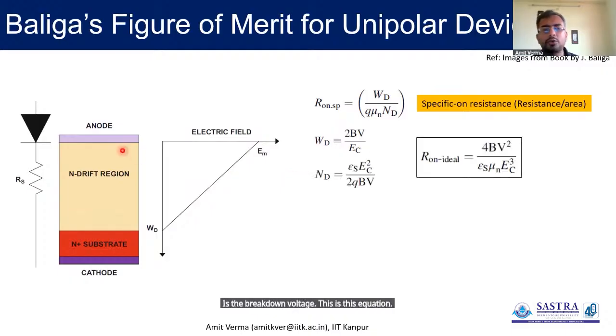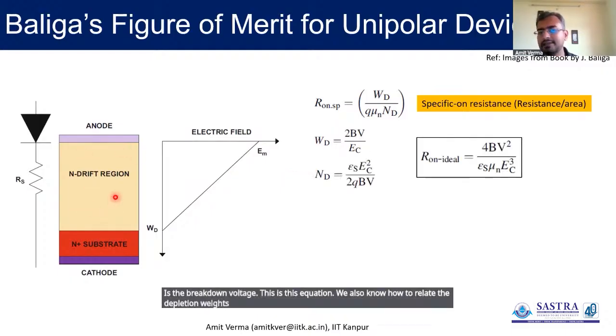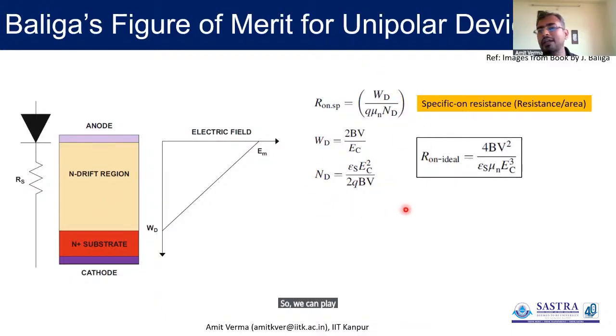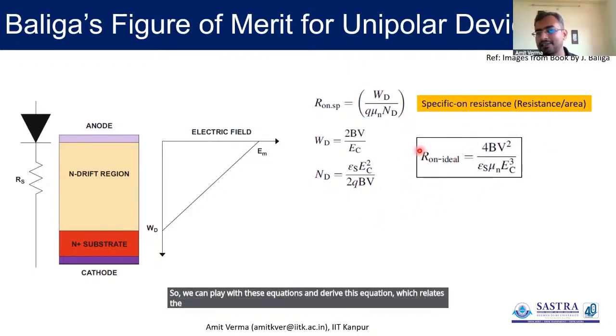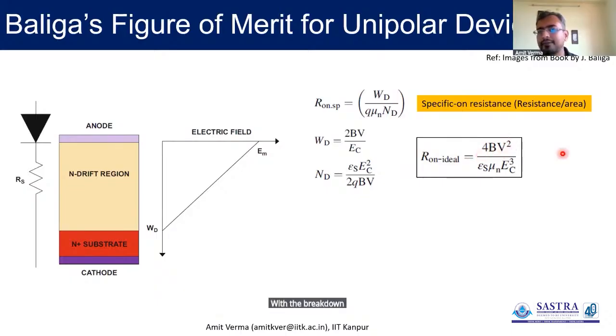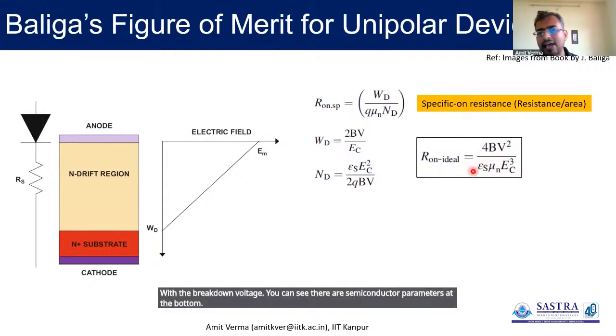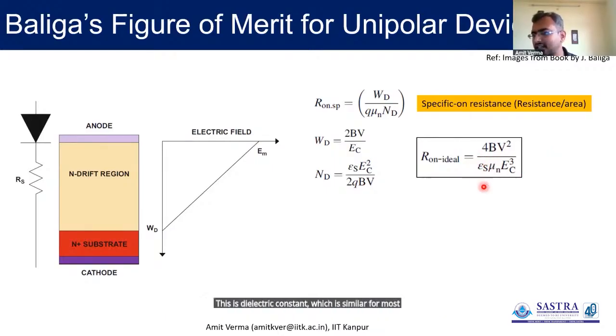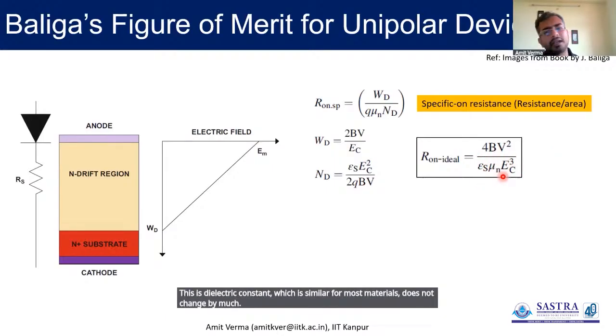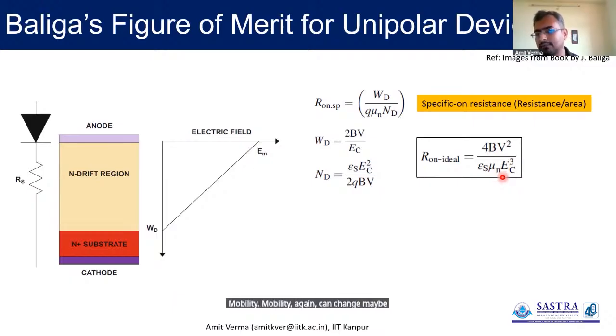We also know how to relate the depletion width with doping. This is standard diode physics. It's something like this. So we can play with these equations and derive this equation, which relates the specific on-resistance with the breakdown voltage. You can see there are semiconductor parameters at the bottom. This is the dielectric constant, which is similar for most materials and does not change by much. Mobility again can change maybe by an order, not beyond that. This is the critical breakdown field. It goes as the third power, the cube, and it's very important in deciding this trade-off.